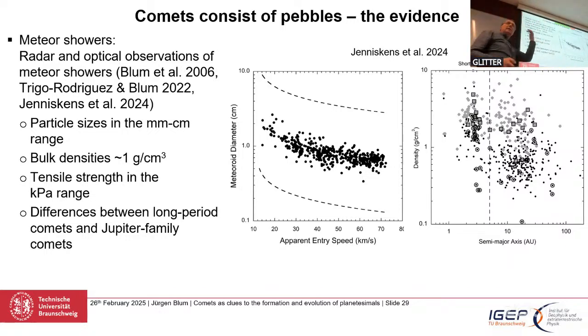But at some times per year, Earth crosses a cometary trail just by chance. And then you see many meteors per minute or per hour instead of a few. That could be hundreds or even thousands, depending on the resolution you're having. And in Peter Jenniskens' paper here, they also determined the density. A solid pebble would have a density on the order of 2-3 grams per cc. There are some here, but most of them are well below a density of 1. So they must be fluffy, large and fluffy.